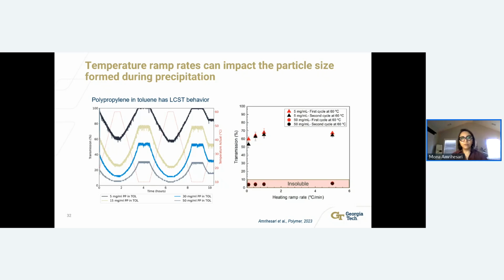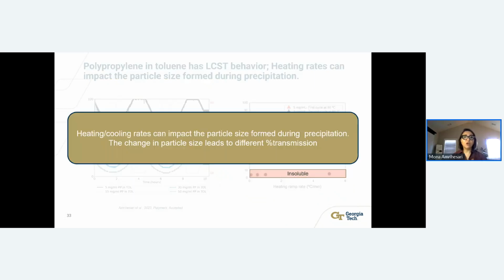On the right side, again, you will see the transmissivity versus heating ramp rate as these polymers start precipitating. We looked at this hot and cold during the precipitation because we believe that the cooling and heating ramp rate can affect the size of the particle as the precipitation is happening. A higher heating ramp rate here led to a smaller precipitate and higher transmissivity in comparison with the lower heating ramp rates. The 50 milligram per milliliter shows the same trend as we have on the top, but it falls within the insoluble region. So again, we are working with large molecules.